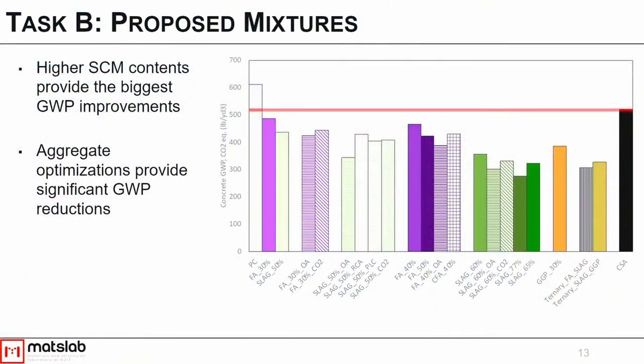With all of that work, we came up with 20 different mixtures that had relatively lower global warming potential than their average Portland cement mixture, which is all the way there on the left. So these are just the broad range of different systems that we use. We were looking at systems with fly ash, with slag, and very high percentages of slag. We actually did some mixes with slag at 77% replacement. Ground glass pozzolan, some ternary blend systems where we used both slag and fly ash, or ground glass pozzolan and slag. And then they also wanted us to look at some rapid repair systems, so we looked at a CSA as well.